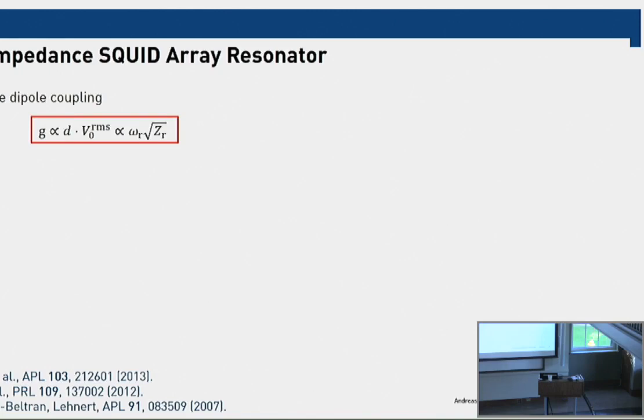Okay, why would using a SQUID array be a good idea for doing a high impedance resonator? The dipole coupling in these structures, or in any structure, is given by the dipole moment of your microscopic degree of freedom and the size of the vacuum fluctuations on your resonator. And you can realize that the size of the vacuum fluctuations on your resonator depends on the square root of the impedance of the resonator that you're using. So you can increase the size of the electric vacuum fluctuations by increasing the impedance of the resonator.